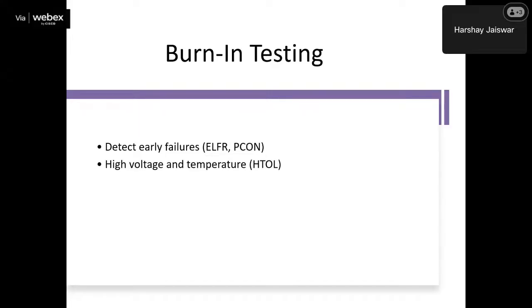This I already covered. High temperature operating lifetime, which is also known as checking pass/fail, where we have a risk of potential overstress. During the burn-in test we also have a risk, because sometimes we have to plan very precisely what voltages to apply on the device so that it is not overstressed. Otherwise, if we overstress the device, it will fail in the beginning, which is not ideal and is also not mentioned in the data sheet. And this is the reason we see a risk in burn-in testing.